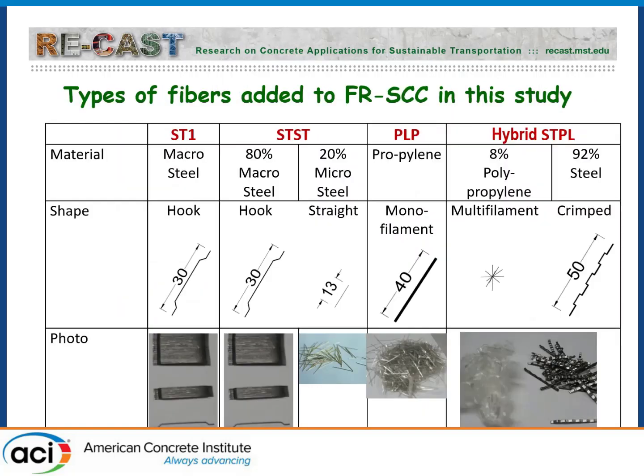We tested a variety of fibers. Dr. Nassif presented a very nice study that went very extensively into various types of fibers and synthetic fibers. Here we did want to use steel fibers. So we have steel fibers that we call a macro fiber. Those are hook end fibers, Bekaert fibers, 30 mm. And then we also decided, because we would like to not only control the macro cracks, but the micro cracks like we do with UHPC, so combine microfibers that are ½ inch in length with the macro fibers.